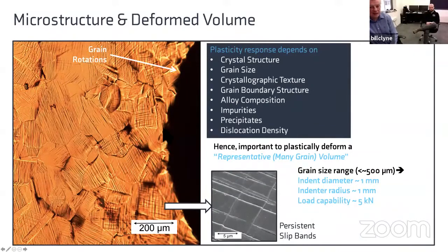And the reason for that is that the way the bulk behaves depends on a number of things. It depends on things like grain size, texture, the structure of the grain boundaries, because that affects the ease of rotation and sliding at grain boundaries. And of course, the usual things that you might expect anyway, dislocation density, precipitates, etc., etc. But it is important to deform a many grained volume.